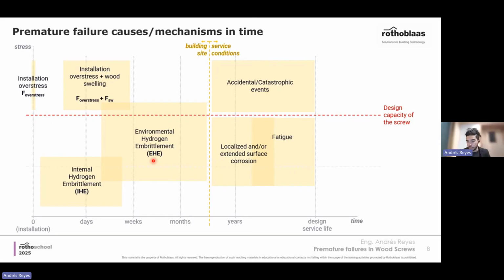Finally, on the building site, what we can have, and that happens from days to months after installation, is environmental hydrogen embrittlement. We will see it in more detail, but it's the other type of hydrogen embrittlement. In that case, we could be talking about a fastener breakage that happens below the design capacity of the screw, but also above it. We're talking here about a combination of factors that could lead to failure above and below.